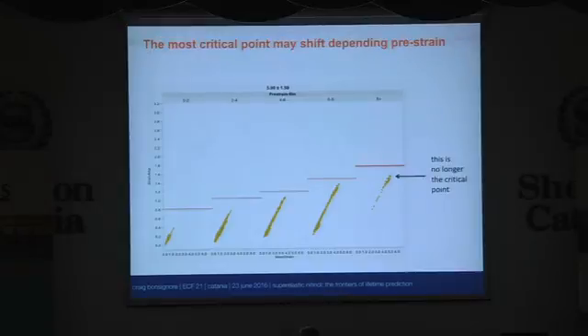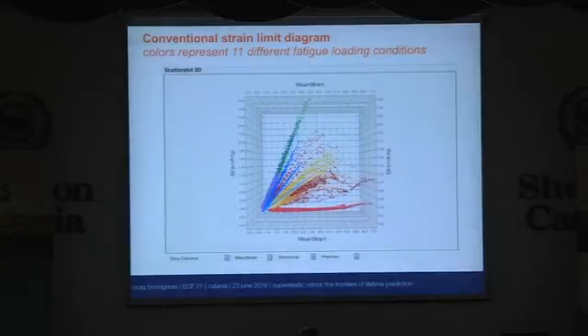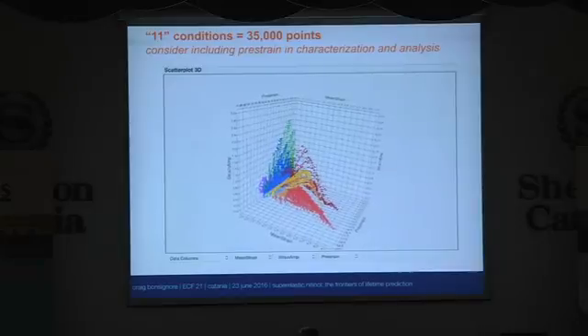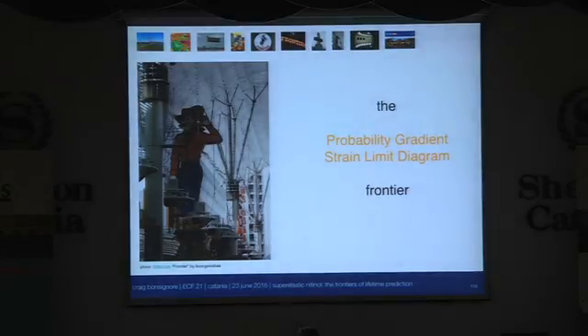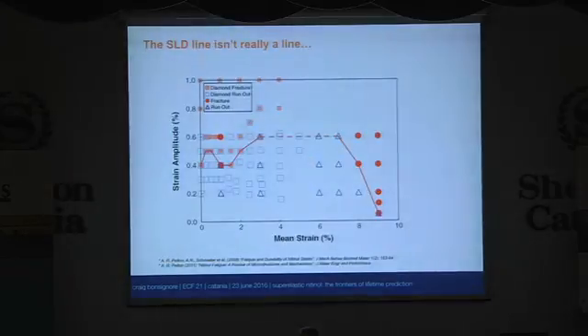Okay? And if now our threshold is changing as a function of the pre-strain level, it may change my prediction about what is the most critical point or what is the most critical condition in this design. So the critical point may shift as a function of this pre-strain, which is a little bit concerning, which means we really need to be worried about it. Okay? So there is this third dimension, if you will, in addition to mean strain and strain amplitude, that we need to think about, and that I encourage researchers in the field to worry about as well. I'm going to skip this, and finally,